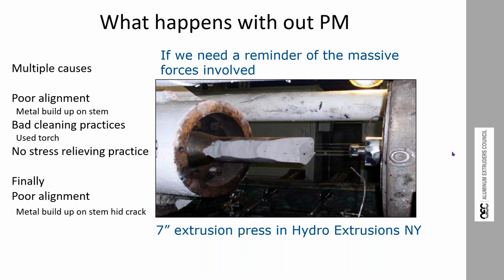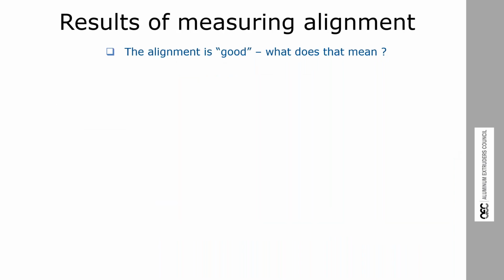Not a healthy situation. There were so many opportunities for this not to happen that they really had to work very hard to get this to happen. If you check your alignment, that keeps your stem clean, so you don't use a torch. But you never, ever use a welding torch or a hot flame on any load-bearing piece of steel on the press. These are highly precise pieces of steel with good metallurgy, which have been heat-treated carefully.